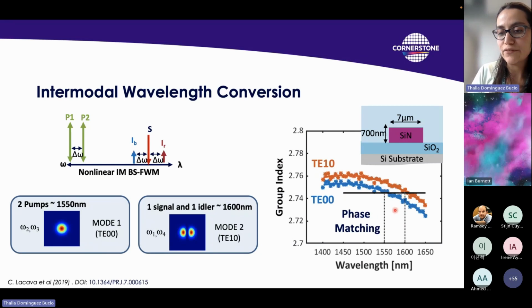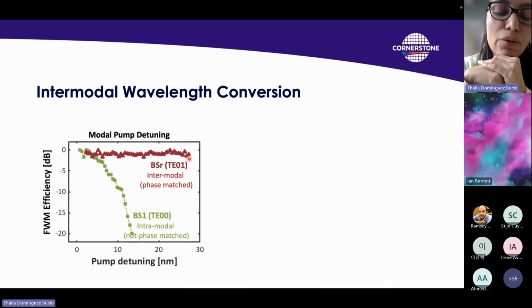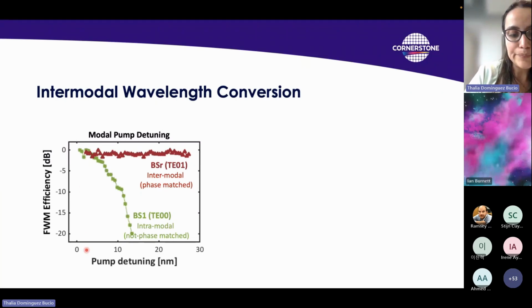In this case, it's close to 1550 and 1600. The advantage of doing this is that if we have a multi-mode waveguide, we can support multiple modes in which we can do this phase matching condition, so that we can extend the wavelength that we're generating to much longer wavelengths. Compared to the intramodal wavelength conversion, which is what I mentioned in the first slide about all optical processing, we see that when we start tuning the pump, so we're trying to move our signal and the idlers that we're generating further away from our pump, the four-wave mixing efficiency starts deteriorating because the process starts being not phase matched.